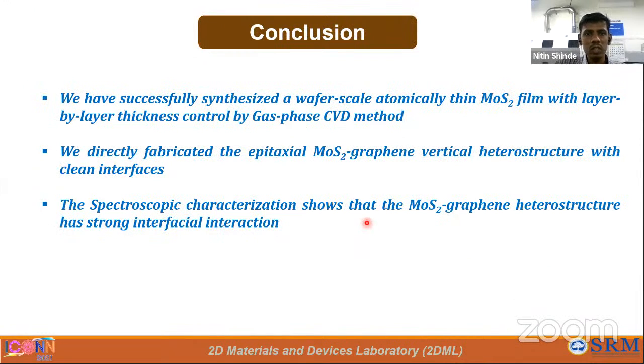And these are the conclusions of my talk. We have successfully synthesized wafer-scale atomically thin MoS2 film with layer-by-layer thickness control by gas phase CVD, and we directly fabricated epitaxial MoS2 graphene heterostructure with a clean interface. And the spectroscopic characteristics show the MoS2 graphene interface has strong interlayer interactions.